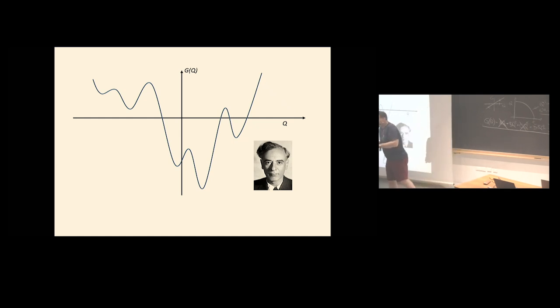The next rather cool thing is to do with the mathematics of what happens through the phase transition. So let's pretend that we've got G(Q) is BQ squared plus DQ to the fourth as a truncated version of the simplest possible Landau expansion. We still don't know very much about it, but let's pretend we do. So under equilibrium, the derivative of the free energy with respect to Q is going to be 0. The gradient of this is going to be 0. You're at a minimum. And therefore, the derivative of our simplified Landau expansion is going to be 2BQ plus 4DQ cubed.